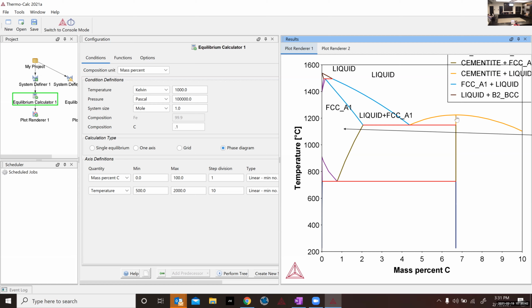If instead you had something that was about 6% carbon right here, and you cooled it down from the liquid phase, you would initially come down here into this 2-phase region, which has liquid on one side and cementite on the other side. So in this little region that looks almost like a triangle with a curved hypotenuse, that's liquid plus cementite. So you form cementite first, and as you go down farther and farther, you get more and more cementite through something called a tie line. You can calculate that. I'm not going to go through it today.